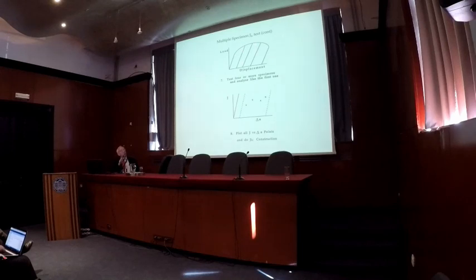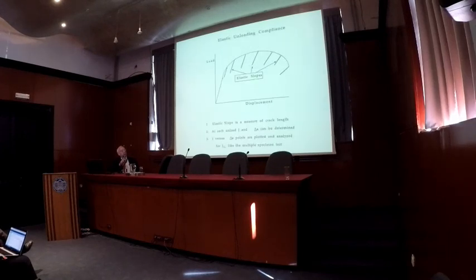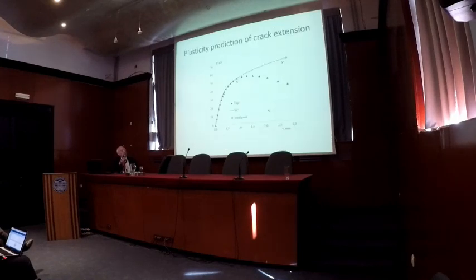So if you do that many times, you get several points. And they have to be within a certain range so that you can do the analysis I'll show you in a bit. Another way is to do little unloadings. And those little unloadings, the elastic slope, gives you a measure of the crack size. So as you load and unload, you can get a measurement of how much the crack has advanced. So if you plot then J versus crack advance, you can do an analysis to get J1C.